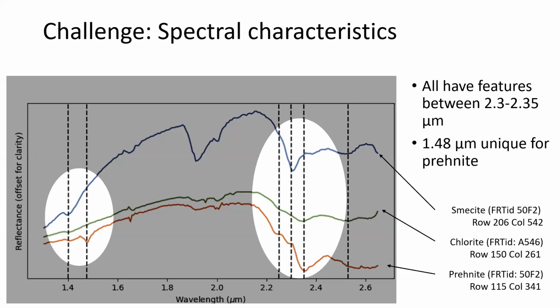This image shows a few good spectra from the CRISM data. I chose those three because these are often grouped together: in blue, the smectite mineral; in green, the chlorite; and in orange, the prehnite minerals. As you have seen in previous presentations already, smectites, especially the iron-magnesium smectites, have a feature around 2.3 micrometers. Chlorite and prehnite are a bit toward longer wavelengths, around 2.35.